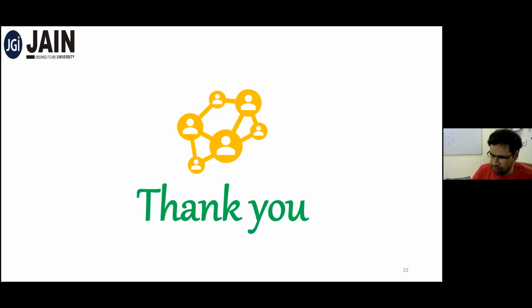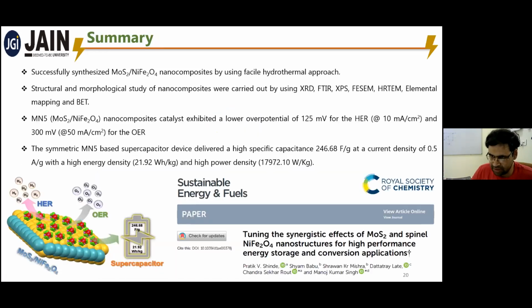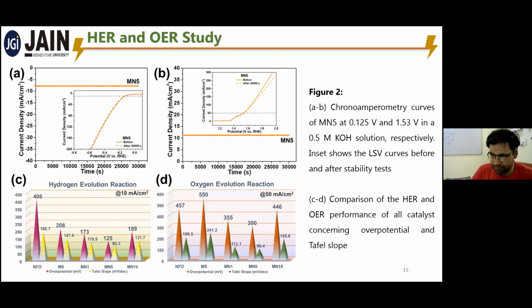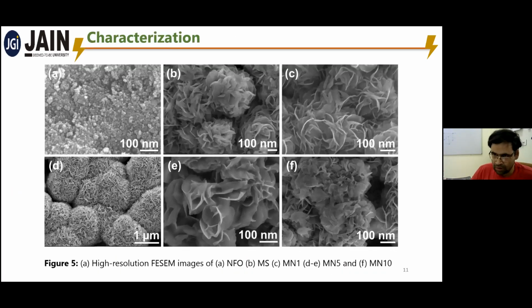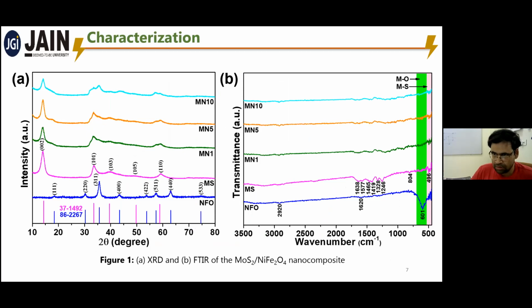Pratik, you go to slide number 7, where you showed the XRD and FTIR. Here nickel ferrite is in crystalline form when it is not in the composite, but when it is in the composite, we don't see any peak, or it becomes amorphous. What is the reason for that? And similar results are obtained in FTIR also.